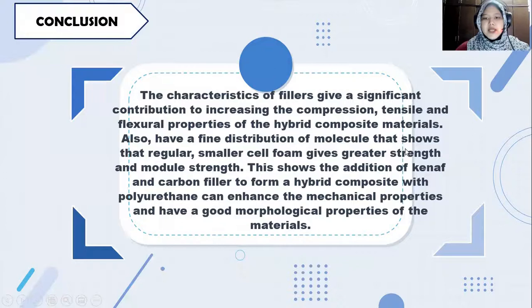For my conclusion, the characteristics of the fillers give a significant contribution to increasing the compression, tensile, and flexural properties of the hybrid composite materials. There is also a fine distribution of molecules, which shows that regular, smaller cell foam gives greater strength. This shows that the addition of kenaf and carbon filler to form hybrid composite with polyurethane can enhance the mechanical properties and also give good morphological properties of the materials.